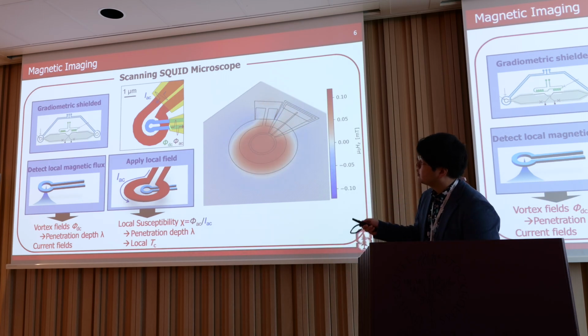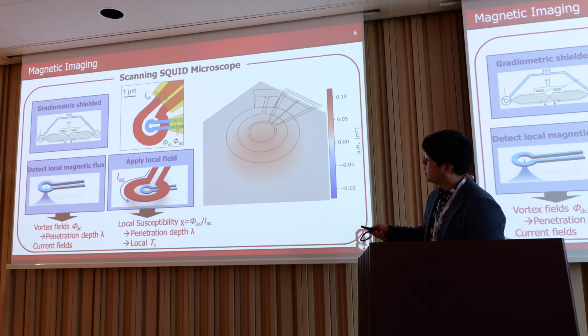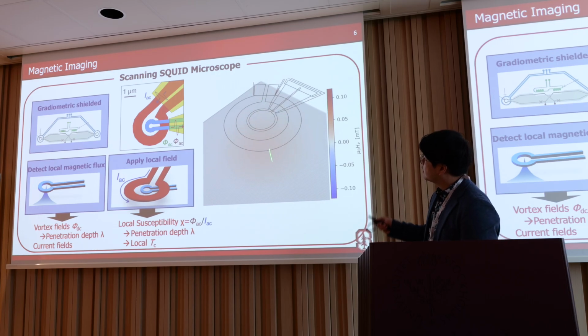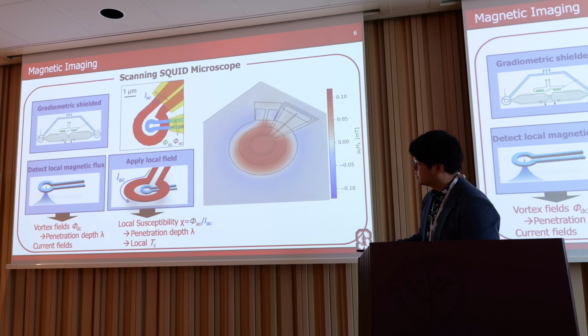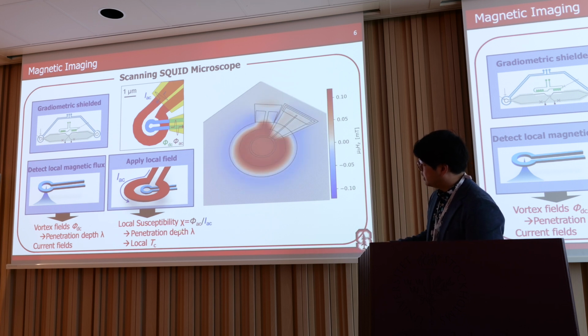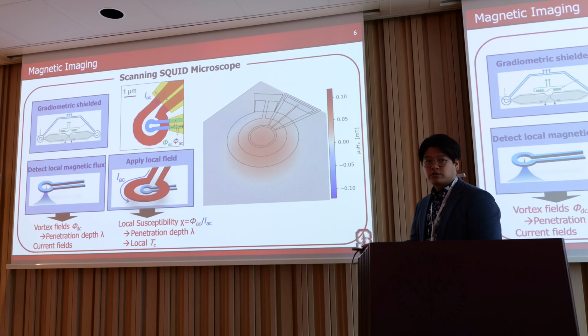It also has a concentric field coil. So we apply the current through the field coil, then we locally apply the magnetic field, and then we detect the local susceptibility, and then it also gets the penetration depths locally.